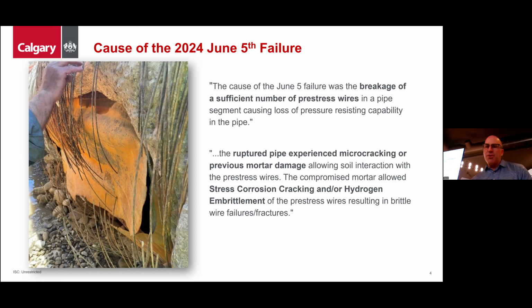Immediately following the rupture, the city requested that Associated Engineering provide us assistance and undertake an investigation of the failed pipe and present the information gained during the exposure of additional pipes, also known as the 5 hotspots, during the initial failure. The cause of the June 5th failure was breakage of a sufficient number of pre-stressed wires in a pipe segment, causing a loss of pressure resisting capability in the pipe.